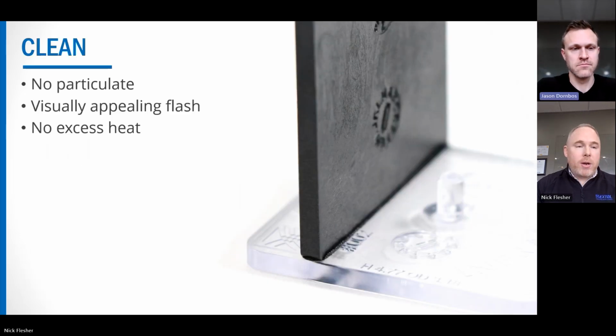So the most common question we get, and we've got a few slides to cover it: when do you use laser plastic welding over your welding method of choice? Ultrasonic is probably the most common that we get because either it's gone sideways a little bit, or maybe there's some particulate, or maybe once that melt starts to happen, it goes too quickly. Vibration is also common that we see. The number one reason is it's clean. There's no particulate.